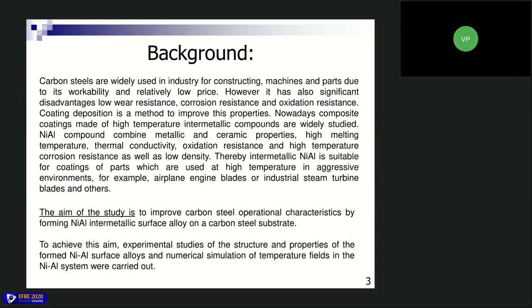Carbon steels are widely used in industry due to their relatively low price and good workability. But this is not the only reason to take this material as samples. Also, it's very convenient for numerical calculations because it consists of mainly one element, iron. So in this work, we tried to make a surface alloy of nickel aluminum intermetallic alloy on a low carbon steel substrate. The aim was to improve the mechanical operational characteristics of the substrate by using the surface alloy.